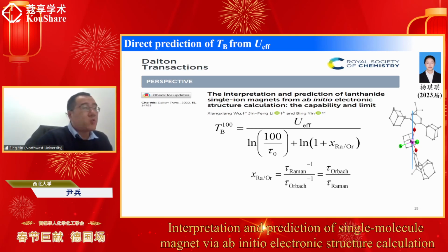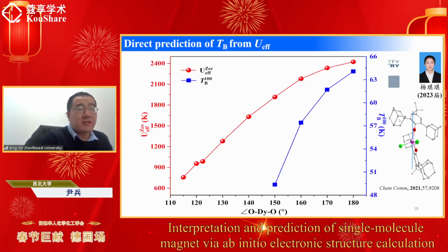And with this method, we predict that for this system, which was published in 2021, if the oxygen dysprosium oxygen angle could be further widened, then the blocking temperature may be increased to more than 60 kelvin. This is the prediction of blocking temperature. That means we suggest that the experimental researchers try to widen such an oxygen dysprosium oxygen angle to get a better single molecular magnetic system.